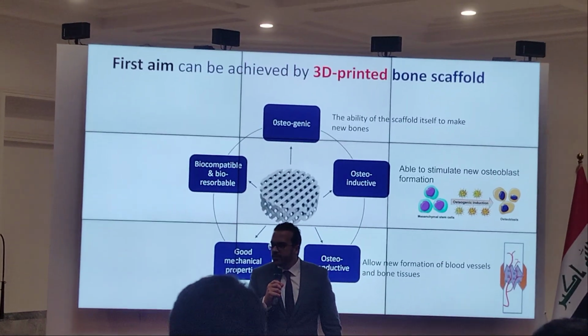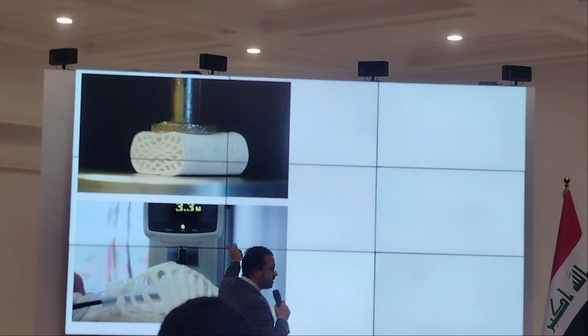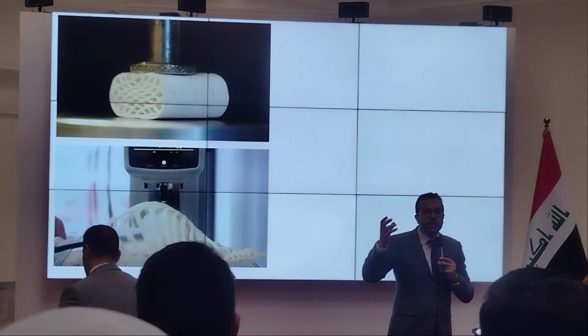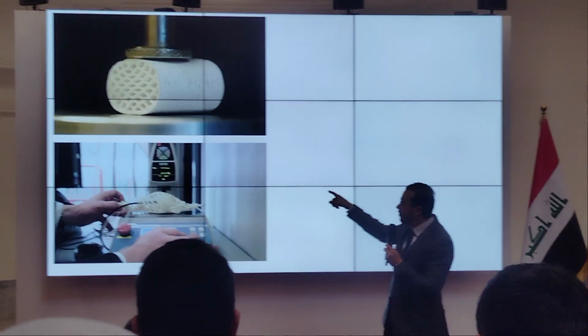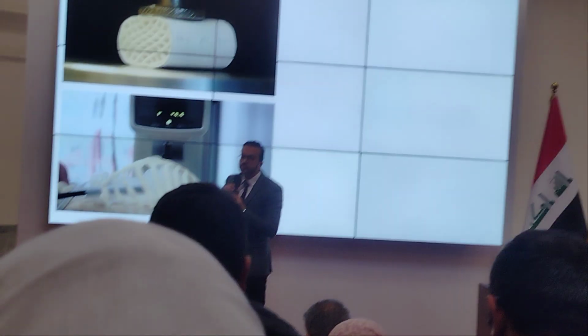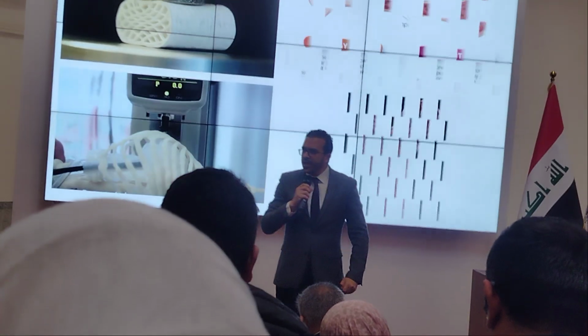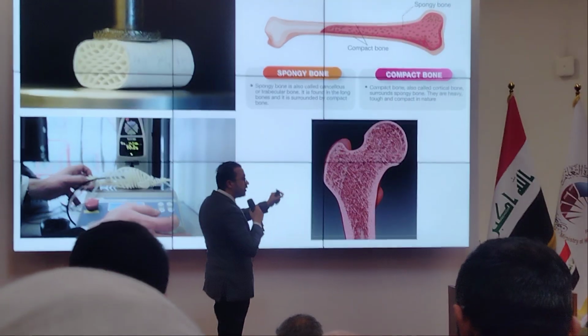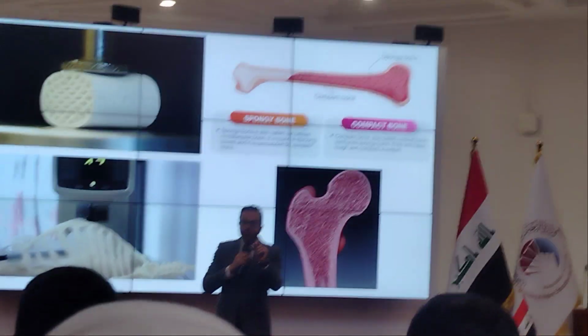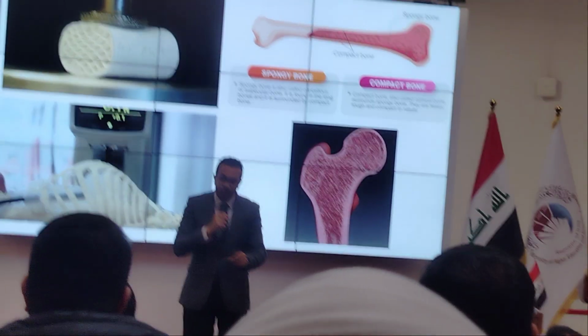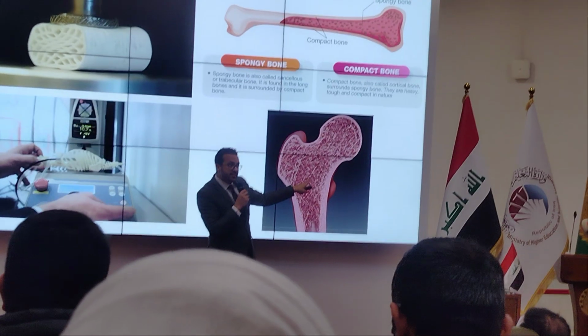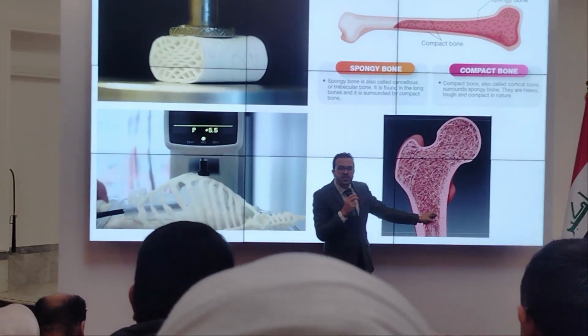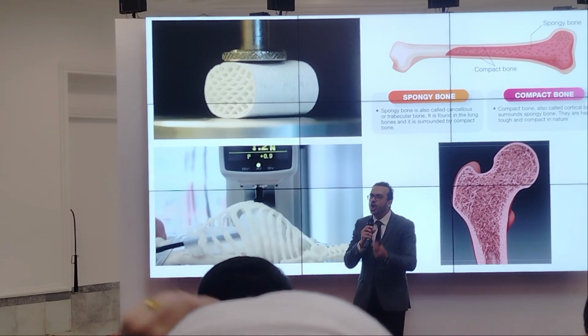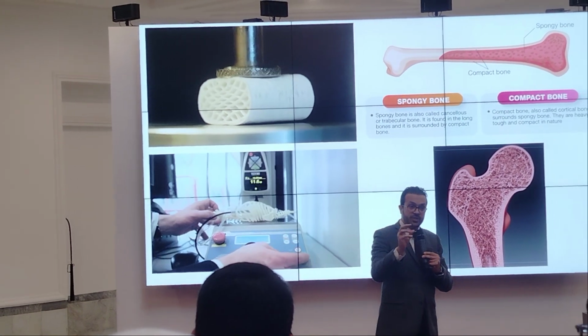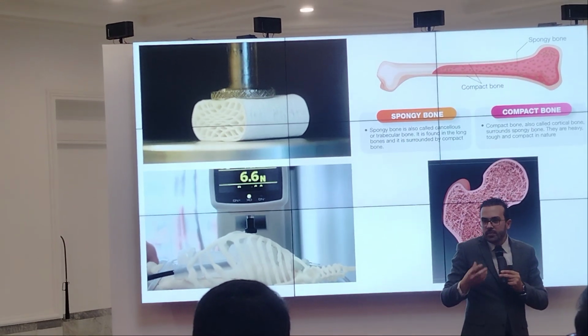Okay, so how does this work? Look at the next slide. This slide just shows you how we can tailor or modulate the mechanical property of the scaffold by controlling the porosity and the infill density. As you can see, controlling the porosity can make this scaffold match the surrounding bone tissue, because the density and porosity of bone is not the same. In any bone, the central part is spongy and porous, and the outer part is more compact. That's why we can tailor the porosity to match the surrounding bone tissue, so it will not be rejected, and this will make life easier with this scaffold.